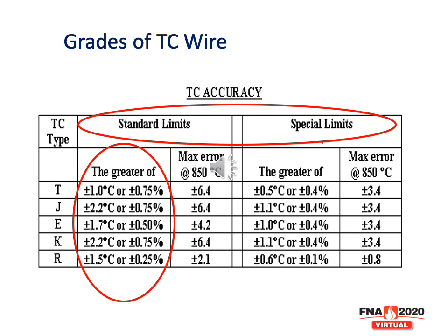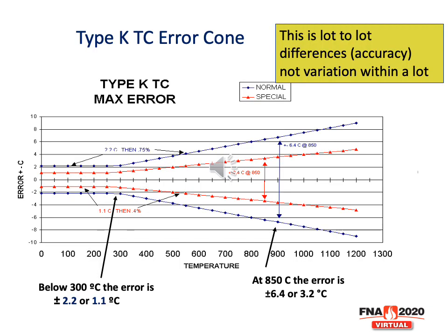But the whole issue is you need to be able to manage the error that you see. For example, for type K, the standard limits are plus or minus 2.2 degrees, or 0.75% of the reading. If we get up to 850 degrees, you can only be accurate within about 6.5 degrees. It's half of that if you go to special limits. If you make a chart showing the error, and we call it the error cone, you can see what happens with type K. Below 300 degrees C, the error is about plus or minus 2.2, or the special limit says 1.1. But as you get above that 300 degrees C, the error cones begin to open up.